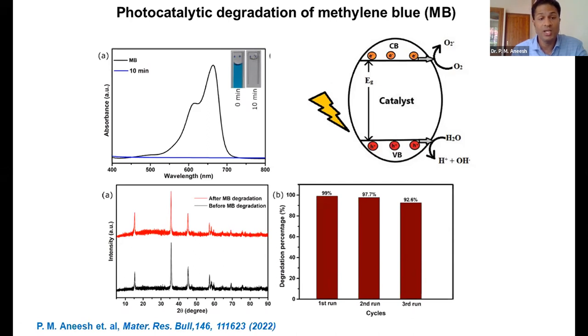We checked the properties after the photocatalytic degradation. Again, we took the XRD of the VS2 sample, and it gives the perfect XRD peaks of VS2 itself. That shows the stability of your nanomaterial even after the treatment with these organic dyes. After that, we did several cycles as well, and you can see the degradation percentage is not reducing much. So you can consider this VS2 as one of the best materials for the photodegradation of methylene blue.